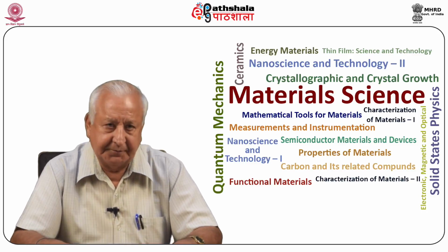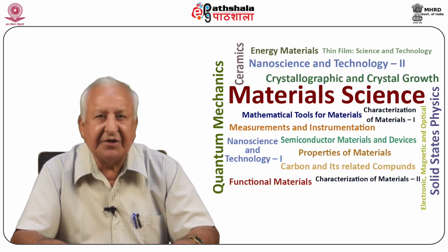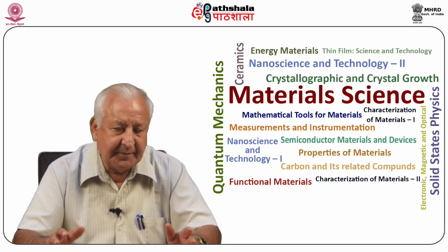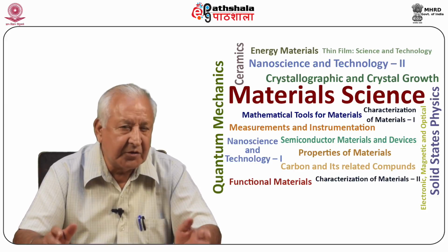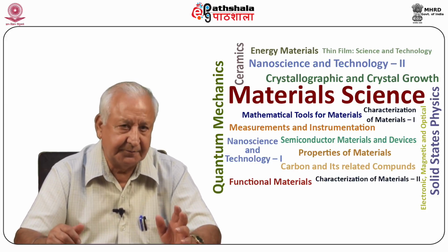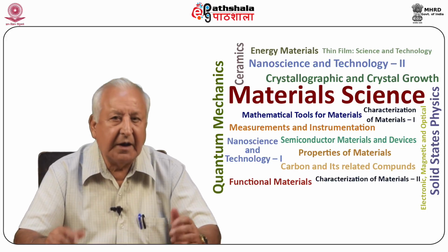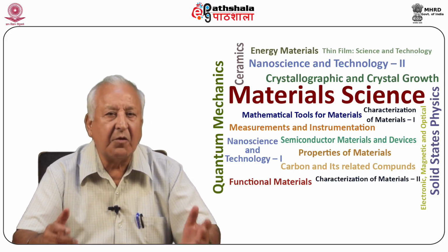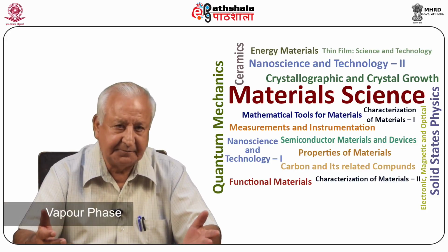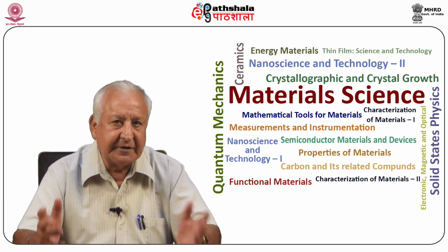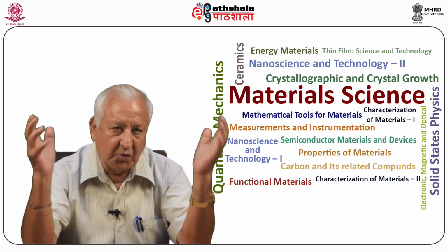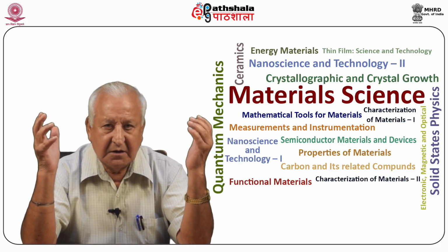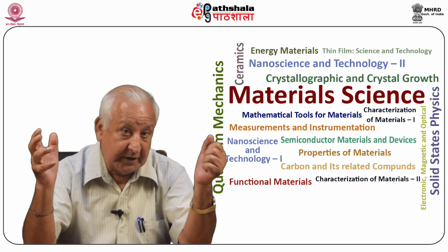Dislocations and crystal growth. In addition to explanation of the nature of slip, yield strength, work hardening, and other mechanical properties, dislocations play an important role in the theory of crystal growth. Crystals can be grown either from solution, or from pure melt, or from vapor phase. Growth from a liquid solution is determined by the degree of supersaturation, while growth from a melt is determined by the degree of supercooling.